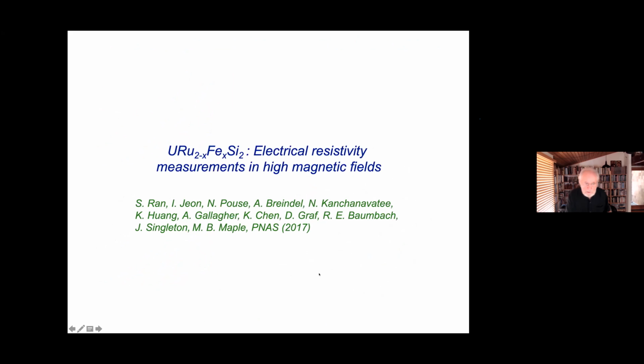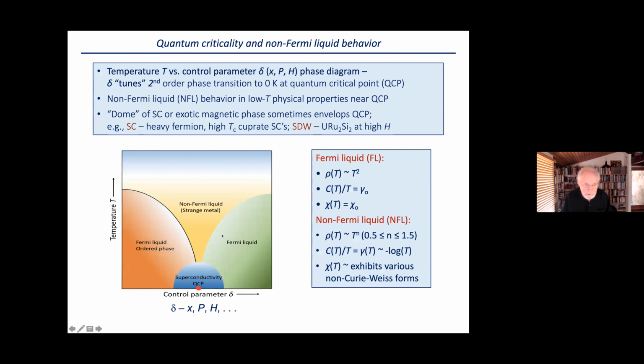Okay. All right. So now let me turn to some measurements in high magnetic fields. Before I do that, let me just say a little bit about quantum criticality. So temperature T versus control parameter, which could be, in our case, composition, pressure or magnetic field, phase diagram. If you consider this, then delta can tune a second order phase transition at zero temperature at a quantum critical point. And so basically what happens is that you find non-Fermi liquid behavior in the low temperature physical properties near the quantum critical point.